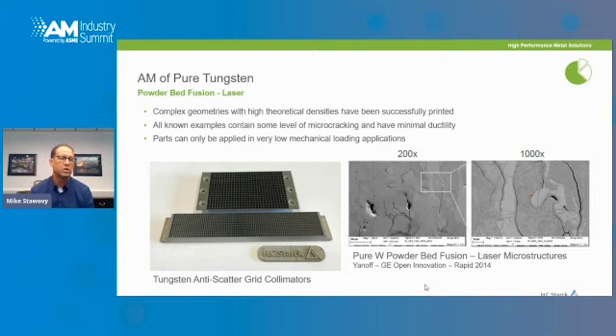that there's a certain level of microcracking that occurs within this material just due to thermal stresses upon solidification. And this material, even though you can print it to high density, it's going to have a minimal amount of mechanical ductility. And so for pure tungsten, in my opinion, there are only applications for very low mechanical loading situations. Some of the photos you see on the left are some examples of anti-scatter grids that are being applied in this kind of situation where there is a low mechanical loading, and all you're looking for is some radiation attenuation within the material. Some examples of the microstructure that has this kind of microcracking are shown in the photos on the right.